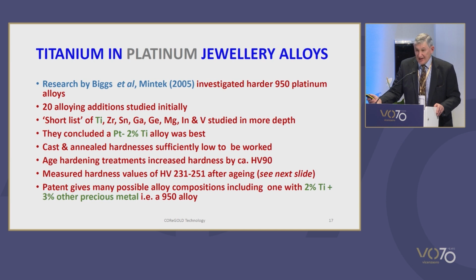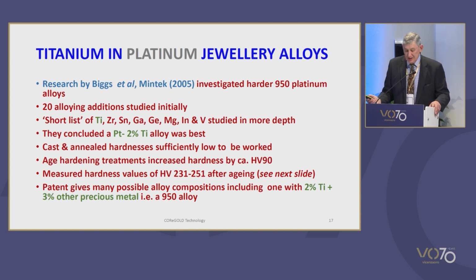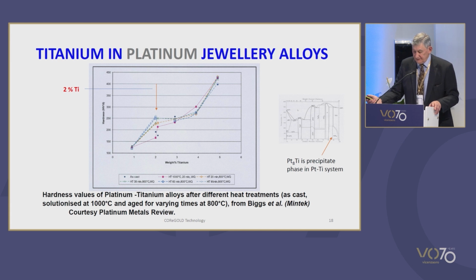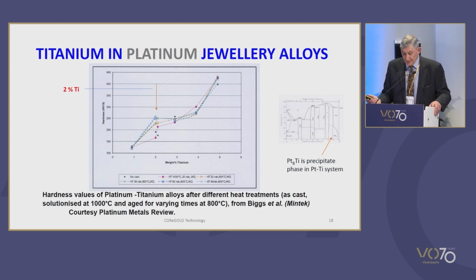Hardness values after aging at 800 degrees of 231 to 251 Vickers were measured, as we can see in the graph from their publication. The patent gives many possible compositions, including a preferred one with a 2% titanium addition and one at 950 fineness with a 2% titanium plus 3% of precious metal. It is not clear whether this work has been developed into a commercial 950 fineness platinum alloy, but clearly shows a lot of promise.